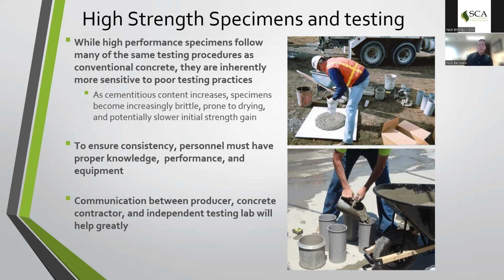Some other concerns that these mix designs can have with higher levels of paste content is that they can tend to self-desiccate. So that can create a brittle and non-representative sample through any of the testing aspects. So ensuring that cylinders are protected from the sun, protected from drying, protected from extreme heat changes or extreme loss of heat is a major issue that needs to be overcome and discussed before any sort of project begins.